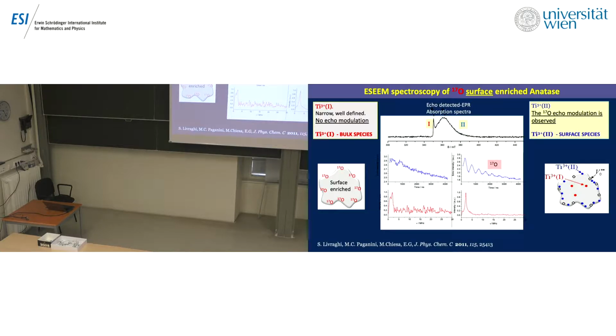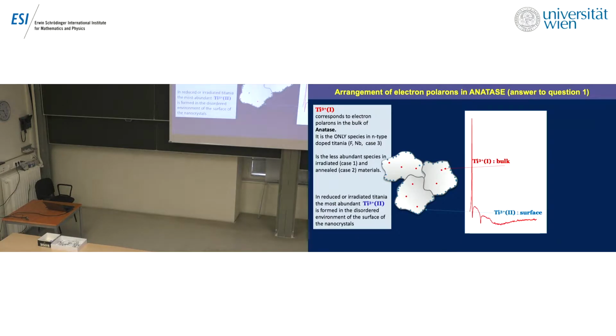Our surfaces are complex, so we are not so lucky to work on single crystal surfaces. There are different phases, defects, vacancies, and this also explains the featureless nature of our signal. So we have answered the first question. And this is, more or less, what I have in mind in terms of model: titanium 3+, blue, at the surface, the red one in the bulk.